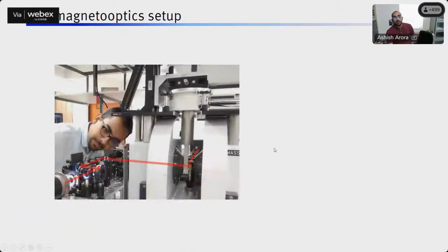Okay, this is a typical magneto-optical setup. So essentially what is happening is the following. There is a cryostat in which the material is lying somewhere inside, and this material is cooled to 4 Kelvin. That's why this is kept in this cryostat and it's in the vacuum. There are two windows around the material. The material lies inside a copper cold finger of the cryostat, which is surrounded by this aluminum shroud, and then there are two windows. And light has to be passed through the material for seeing the Faraday effect.